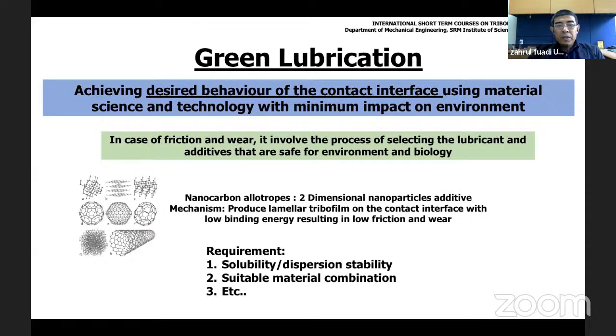And then you will require a suitable material combination, because sometimes you find a publication where a very good tribofilm is formed on some contact interface using this and that material. But what you tell people is that you try, and if you get a good result, then you're right. Most of the time when you try, you will not get a very good result. So you have to look for a suitable material combination that can work with the type of solution or additive you are using.